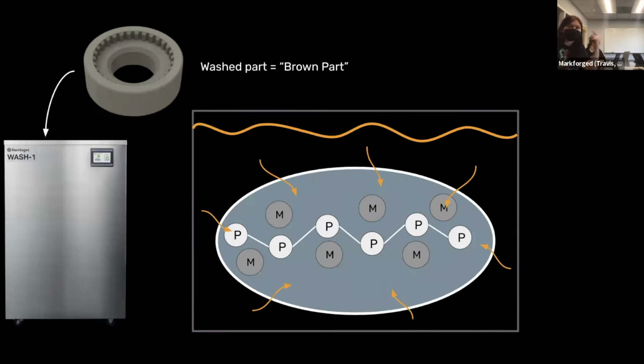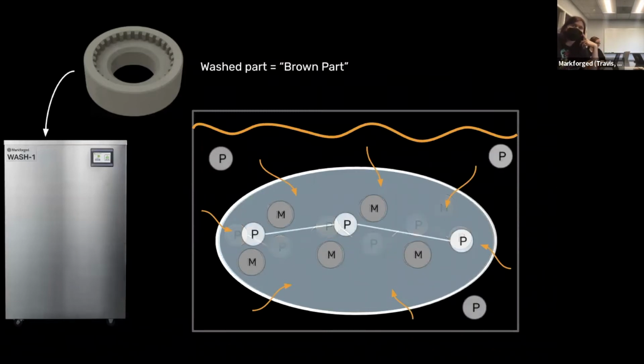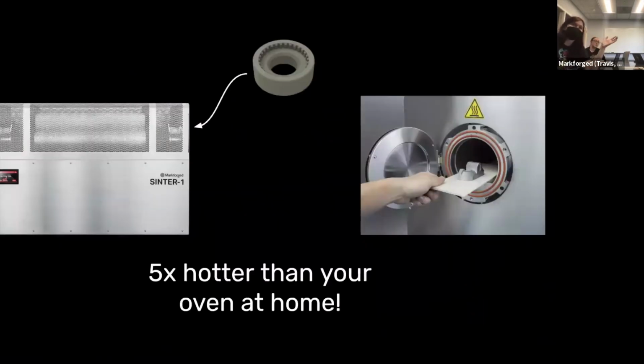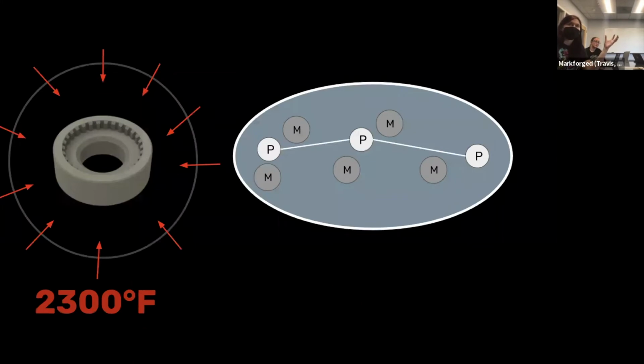Then it goes into a sinter, which is 5 times hotter than your oven at home. So it goes in there, it gets very hot and it causes all of the metal to fuse together. This also means that there are lots of considerations with printing metal parts, like you have to scale them up when you print them because they shrink down once there's nothing else there when they all fuse.